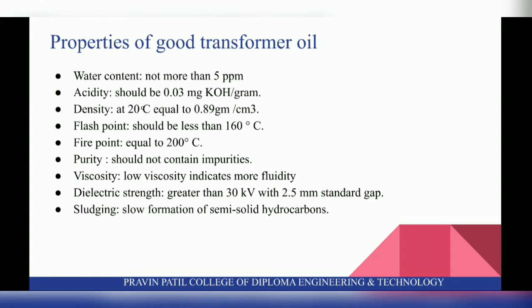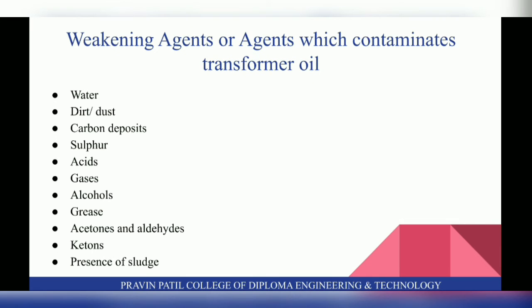And last one is sludging. Sludging means the slow formation of semi-solid hydrocarbons. They block the passage of cooling oil. When the bright copper surfaces are exposed to oxygen, the process of sludging accelerates. The remedy is to use oil which will not contain sulfur or its components. The contact of copper surfaces with oxygen should be avoided by providing a conservator tank.